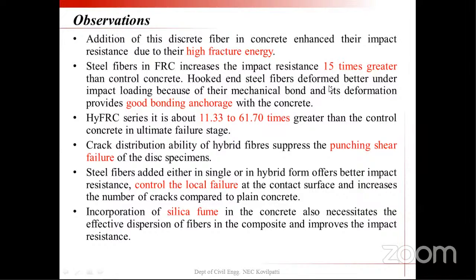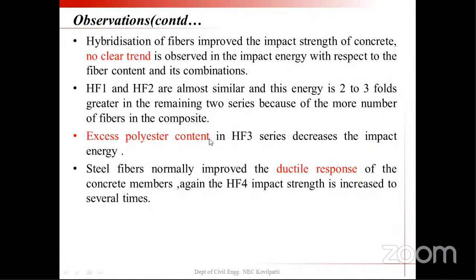The energy has been increased 15 times. It's because of the good bonding anchorage. And in hybrid FRC, the improvement is up to 62 times. While observing the failure pattern, the punching shear failure is observed on the disc specimens. And steel fibers provide better impact resistance to control the local failure. In addition to that, silica fume also necessitates the effective dispersion of fibers throughout the composite and improves the impact resistance. And for hybridization, no clear trend is observed with respect to the fiber content.